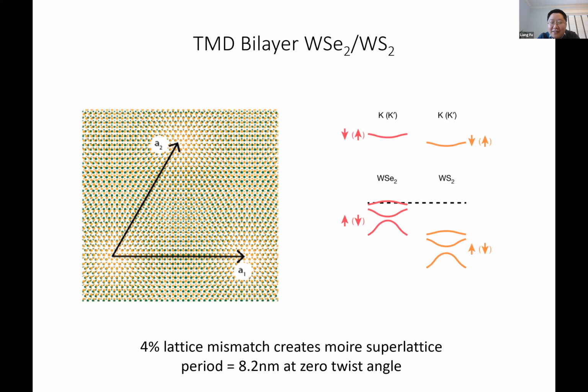and the gate voltage. Now what's interesting is that in these TMD materials, the alignment between the 2 layers has been measured through the second harmonic generation. In both of these experimental works, you have 2 layers, WSe2 and WS2, they overlap in some region to form this heterobilayer, but they also extend right into their own regions.